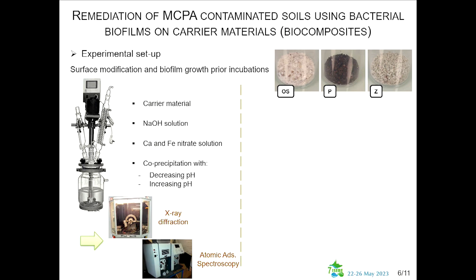This is made in such reactors with a double envelope, let's say, to control the temperature thanks to an apparatus that sends water at the appropriate temperature into the reactor. So this is made with the two protocols that I described. And after that, we sieved the suspension obtained to be able to determine the nature of the oxide that was made. And this is made thanks to X-ray diffraction.